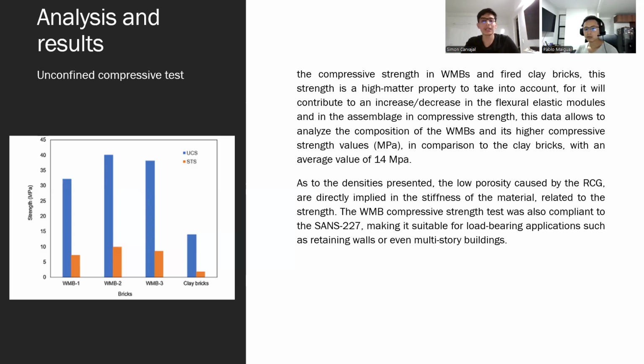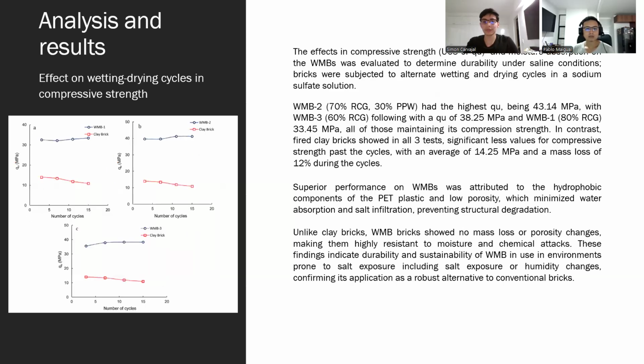This shows that the compressive strength in the WMBs is higher, and due to this durability, and as per the densities presented, the low porosity caused by the RCG is directly implied with the stiffness of the material, and it's also related to its strength. Now, for effects of wetting drying cycles on compressive strength, we can see in these graphs A, B, and C.